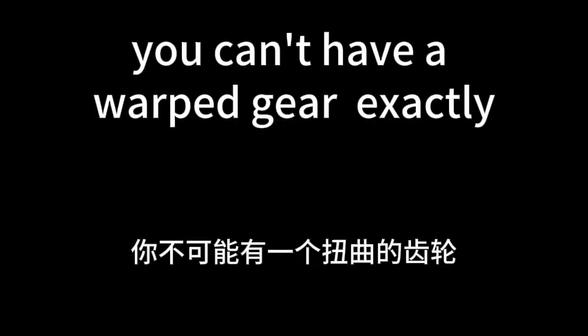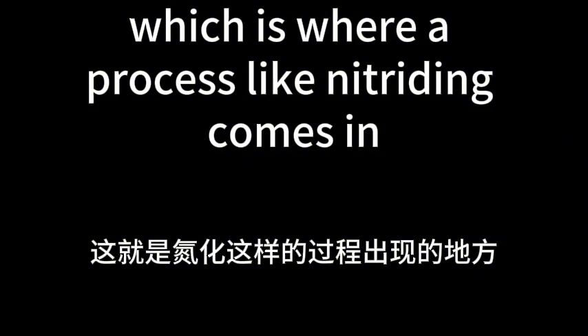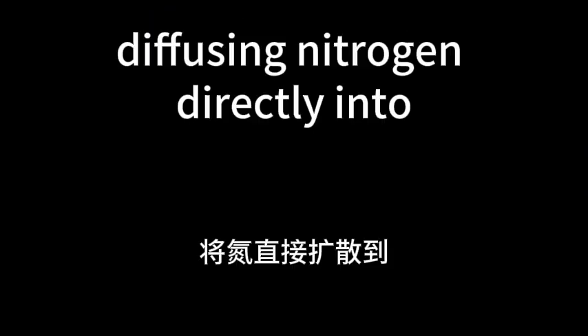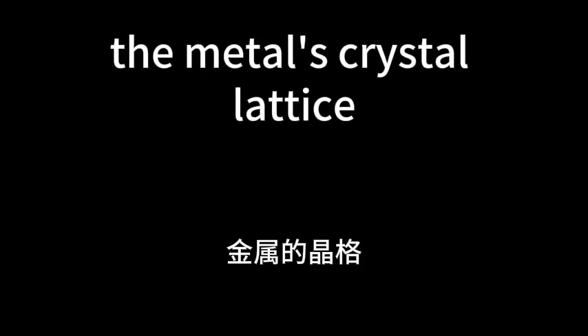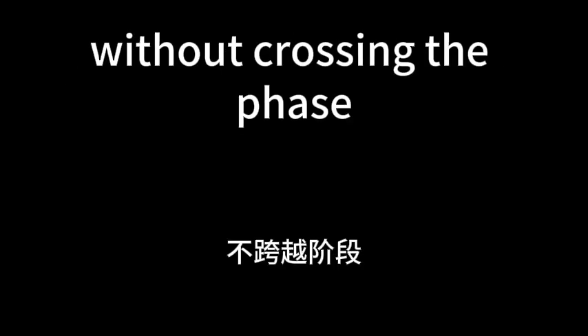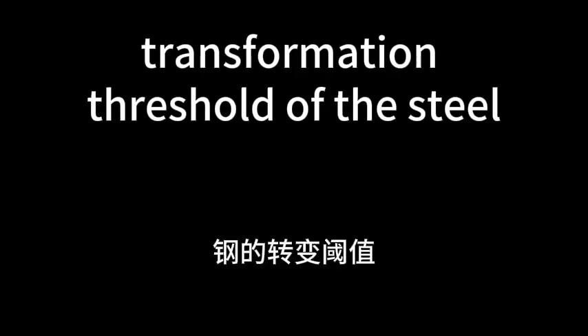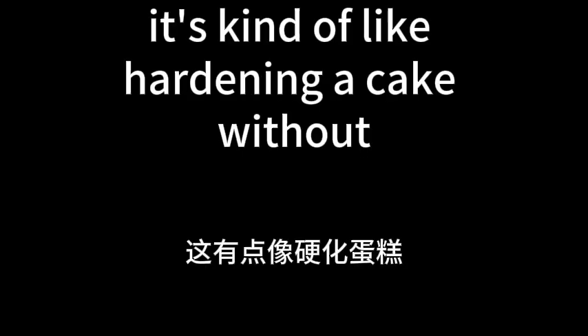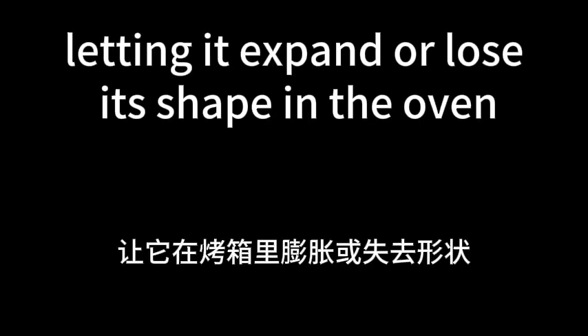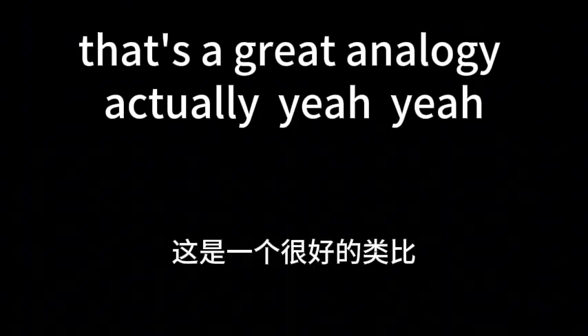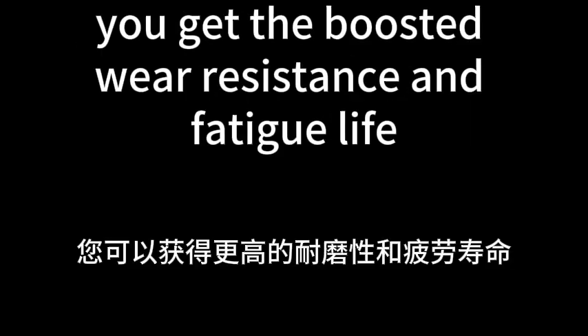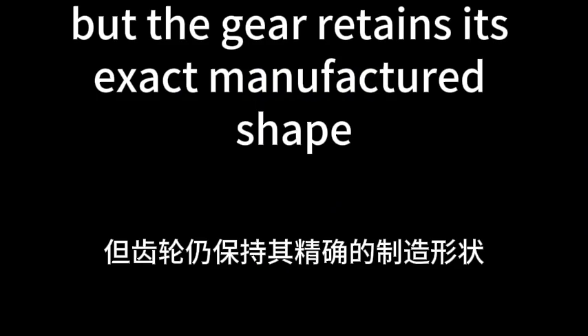Yeah, you can't have a warped gear. Exactly. Which is where a process like nitriding comes in. It operates at a low temperature, diffusing nitrogen directly into the metal's crystal lattice without melting it. Right, without crossing the phase transformation threshold of the steel. So it's kind of like hardening a cake without letting it expand or lose its shape in the oven. That's a great analogy, actually. Yeah, you get the boosted wear resistance and fatigue life, but the gear retains its exact manufactured shape.